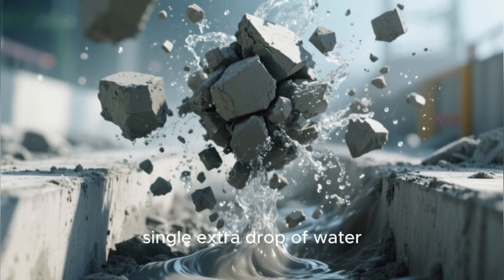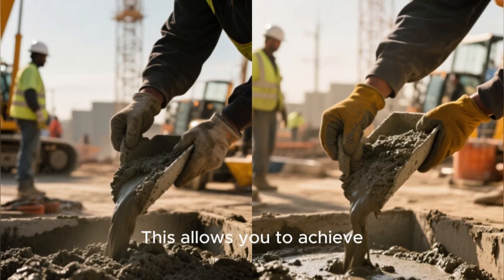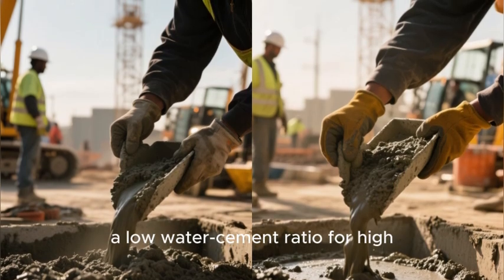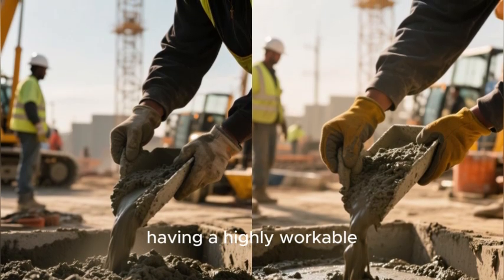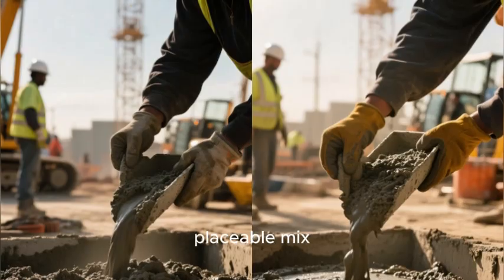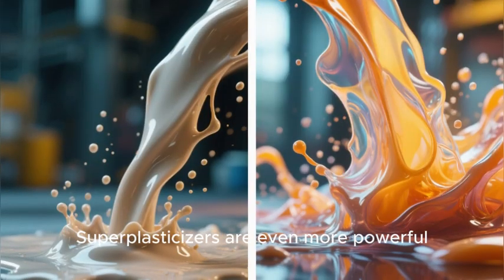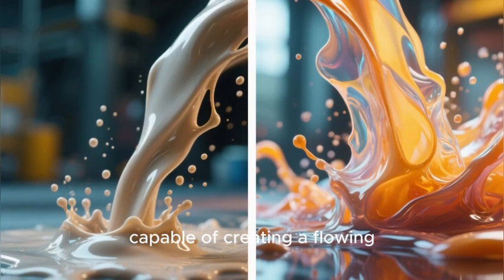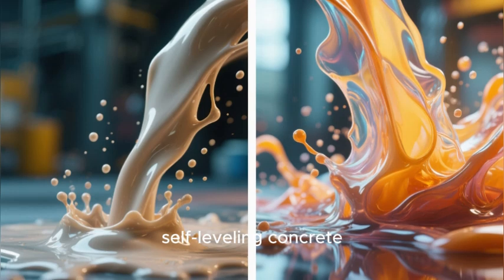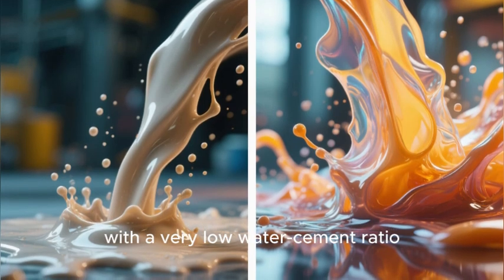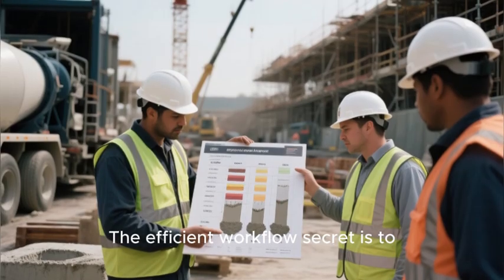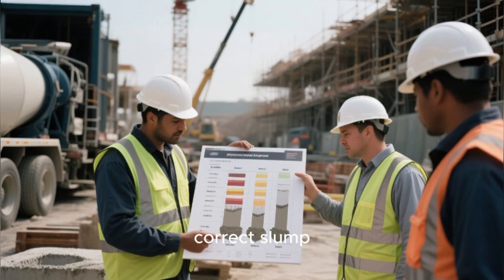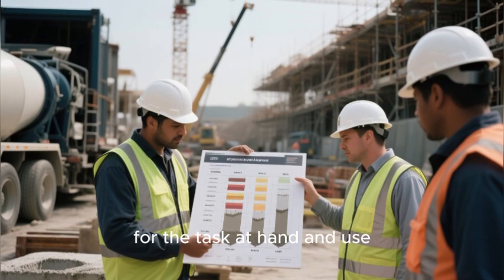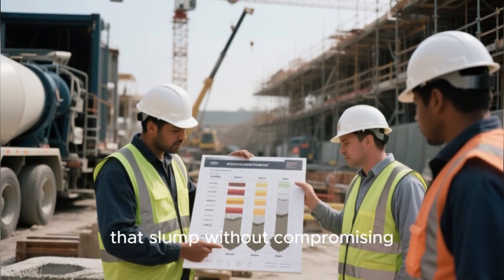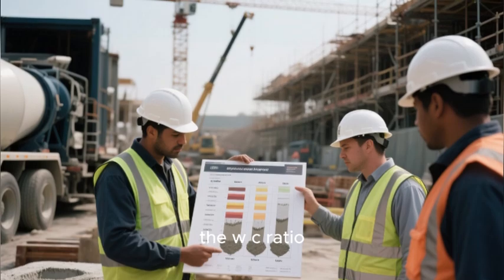and making the concrete fluid without adding a single extra drop of water. This allows you to achieve a low water-cement ratio for high strength while still having a highly workable, placeable mix. Superplasticizers are even more powerful, capable of creating a flowing, self-leveling concrete with a very low water-cement ratio. The efficient workflow secret is to order concrete with the correct slump for the task at hand and use admixtures to maintain that slump without compromising the WC ratio.